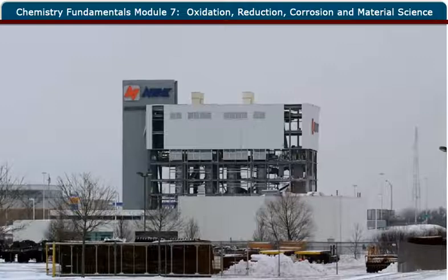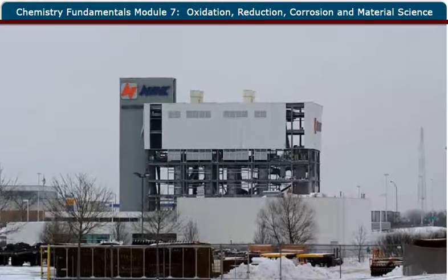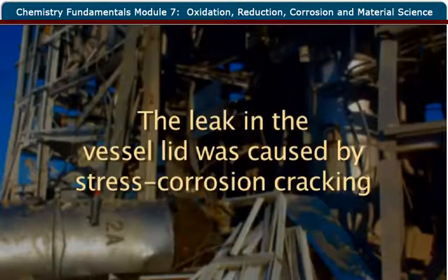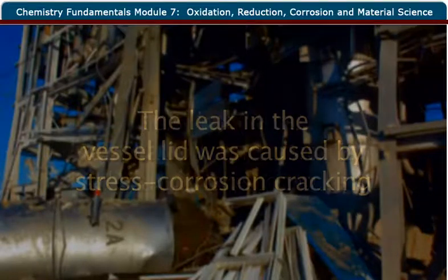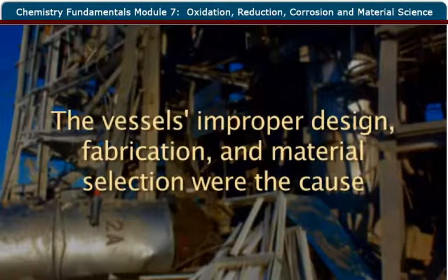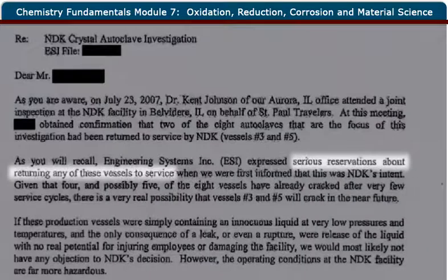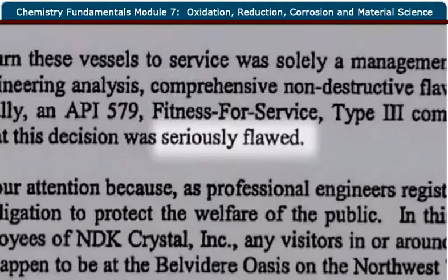A third-party consultant, hired by NDK's insurance company, determined that the leak in the vessel lid was caused by stress corrosion cracking and concluded that the vessel's improper design, fabrication, and material selection were the cause. Later, in August of 2007, the insurance company informed NDK in a letter that its consultant had serious reservations about returning the pressure vessels to service, and that a decision to do so would be seriously flawed.